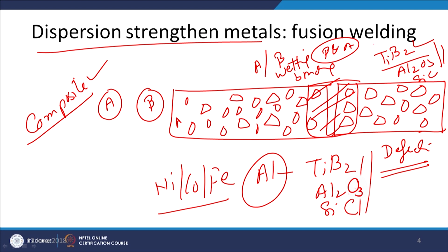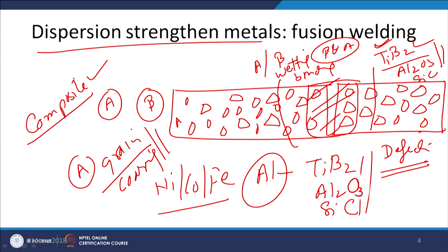So, the particles, these reinforcing agents, may lose their identity, and so their effect in the weld metal may also be lost, or it may be compromised badly. While the variation in the properties in the heat affected zone of the dispersion strengthened metal system may not be appreciable, except that the metal matrix may get coarsened. So, grains of the metal A may get coarsened due to the application of heat. Such coarsening of the metal matrix may lower the hardness. However, such a reduction may not be appreciable.